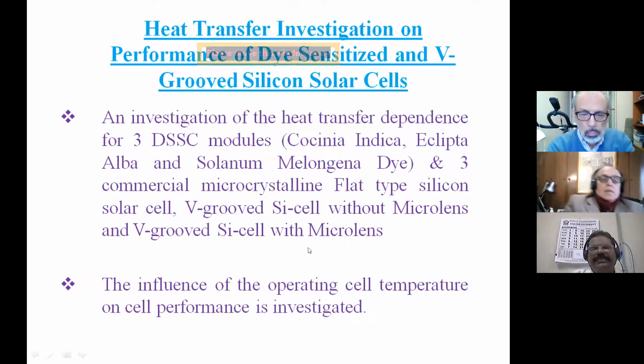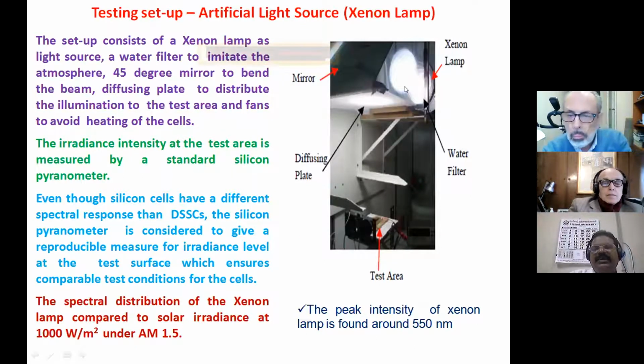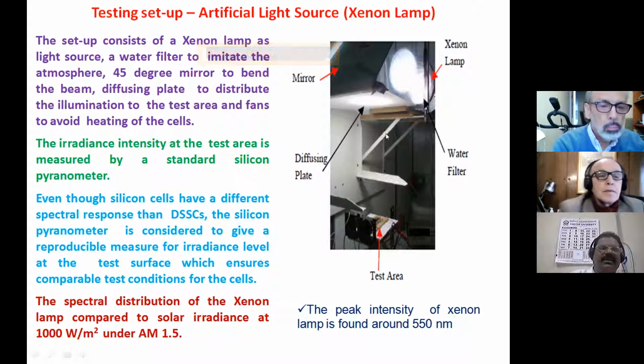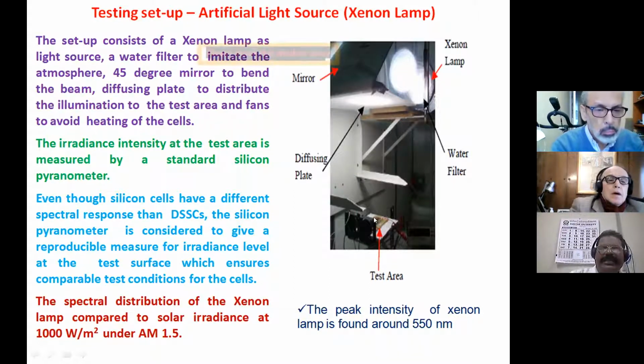So this heat transfer study was also performed for the fabricated silicon solar cell as well as the dye-sensitized solar cells. So what is happening here? This setup consists of a xenon lamp as a source, used to imitate sunlight. We have used the xenon as a source, with some filters to create atmosphere conditions like air mass 1 or 1.5. One mirror is kept at 45 degrees to distribute the illumination on the test area. So this is the test area, and fans to avoid heating the cell are also arranged.